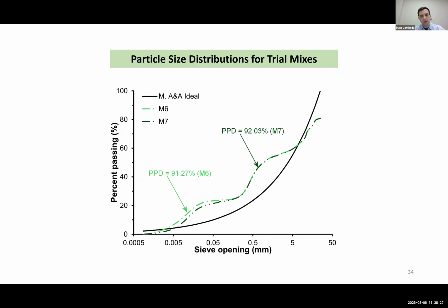And then here's the resulting mixes that we did. Forgive the numbering, but there were trials before 6 that didn't make the cut. So 6 and 7 were the ones that we moved forward with, and you could see the relatively high particle packing density above 90% for both of them. And it's doing a pretty decent job of hugging that ideal curve from the Andreasen model, which is why we decided to move forward with it.